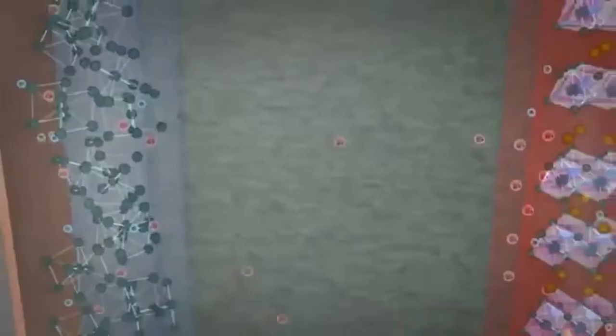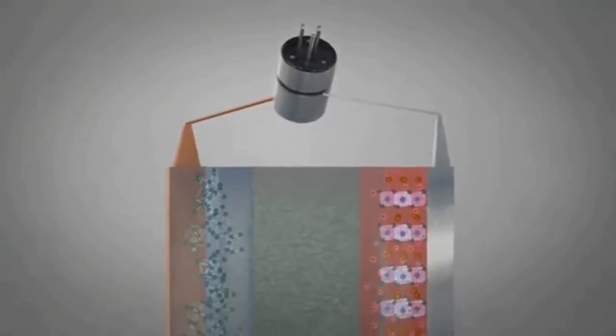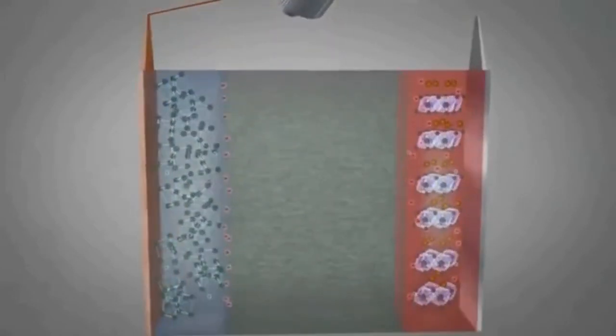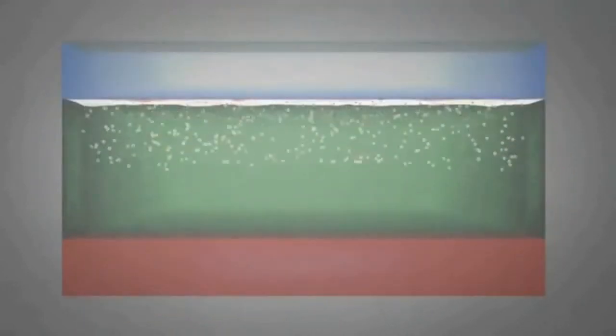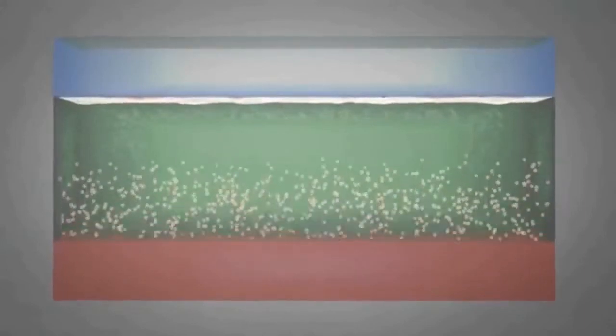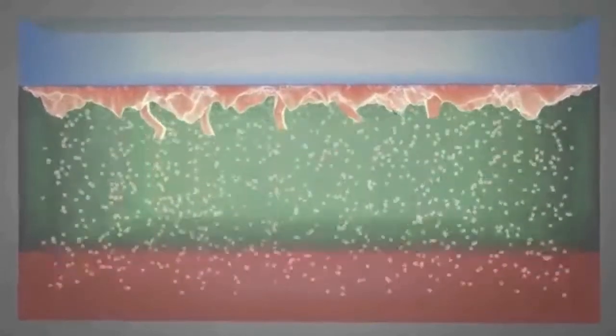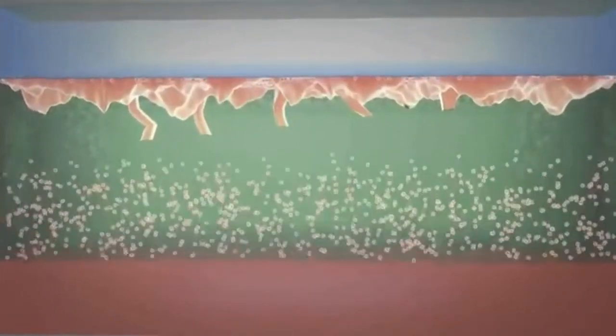To take high-resolution video images of what is happening to the electrodes and link that with what is happening electrochemically. During discharge, lithium is stripped off the anode surface and migrates to the cathode. During charge, lithium is deposited back on the anode. Repeated cycling can result in stripping and redeposition that roughens the surface. The roughening changes the electric field and draws more metal to spikes that are beginning to grow. These can grow with tremendous mechanical force, puncture the separator, and directly connect the anode with the cathode, which can create an internal short circuit. This can lead to an uncontrolled discharge reaction which heats the cell and causes additional exothermic reactions, leading to what is called thermal runaway.